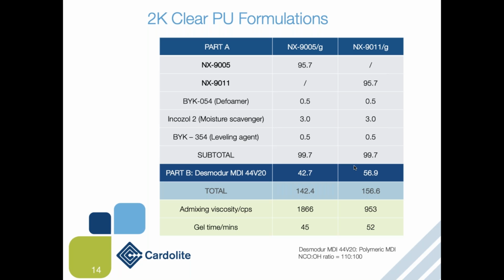NX9005 and NX9011 can be formulated to make a 2-component clear PU formulation for flooring applications. So to share that utility, we made a very simple formulation here. We used a defoamer, moisture scavenger, and leveling agents, and cured with polymeric MDI. And as you can see, low viscosity can be achieved, and also appropriate gel time and pot life.